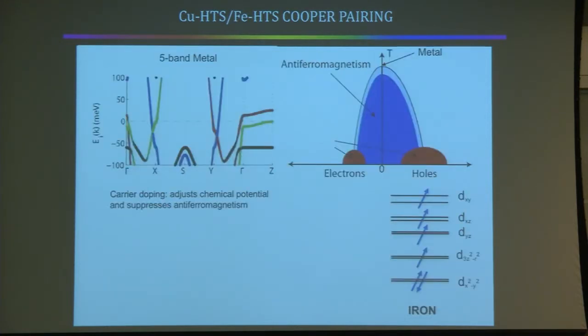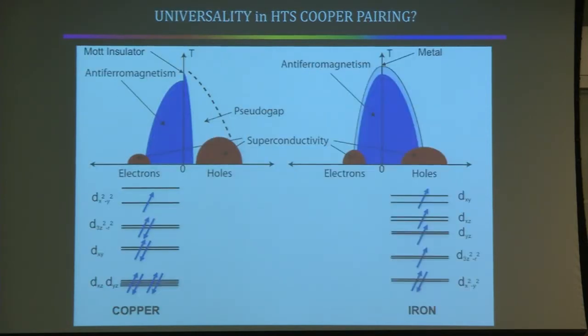However, the other compound we have available is iron. So the iron compounds are metals. They're so-called bad metals. They're reasonably poorly conducting metals, but they're certainly not Mott insulators. You can drive charge through them relatively easily, and we know what the band structure is. So what carrier doping does is actually it moves the chemical potential through this band structure, at least if you take a free particle point of view. So that appears dramatically different than this argument.